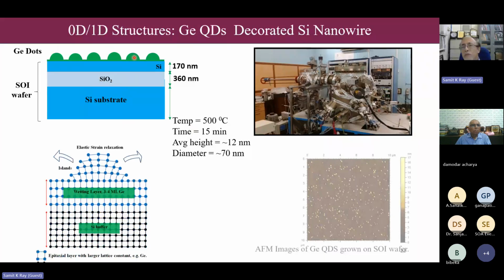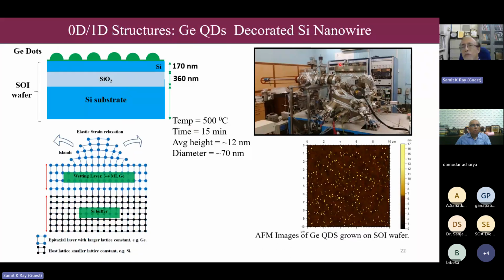And we grow this material by a technique in our lab, called molecular beam epitaxy. It was actually installed more than 35 years back, when Professor Chopra was here for the superconductor research. Then we converted to semiconductor. So when you grow this germanium on silicon, their atomic diameter is different. There is a mismatch of their so-called atomic diameter, and all this material has to be grown in single crystal form. So what happens, we start growing the material, lot of stress is developed.